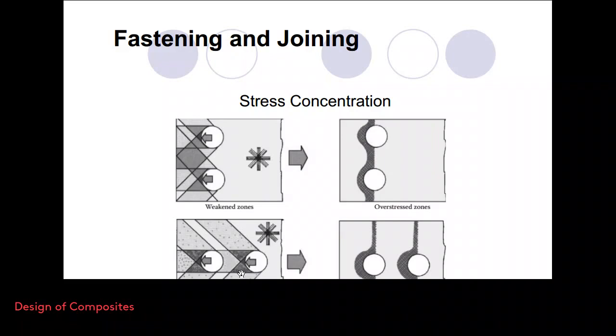Moreover, even though in the zones next to this zone the stress is higher, you still make the design with respect to this area, and in fact you have much lower stresses in this region on either side of the hole. As a result, this type of design is preferred compared to this type of design, because the load bearing capability of this design is much higher compared to this one. So we unlikely see a failure here or here.